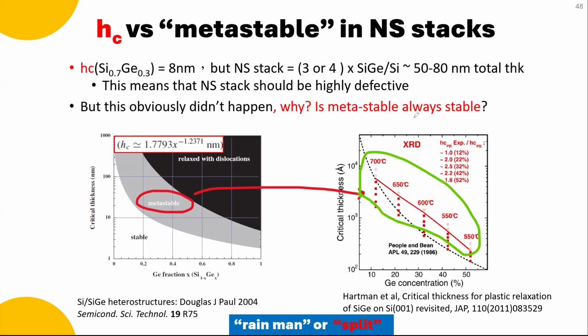So you are in this region, but it's very little defect. In theory, it could be very defective. It depends on how you grow it. And this metastable region is the region we're talking about. This region is temperature dependent, depending on how you grow it. Metastable means that it's not bad, but it's not good either. If you go over to the dark area, you are relaxed with dislocation. In here, you kind of hang there. That's why it's called metastable, meaning that it's not stable, but it's not relaxed yet. It's somewhere in between. And if you don't treat it right, it can easily be defective. So the question is, is metastable always stable? It depends on temperature, of course, right? So it's not.